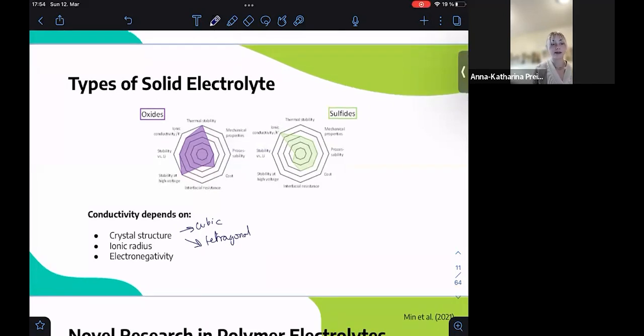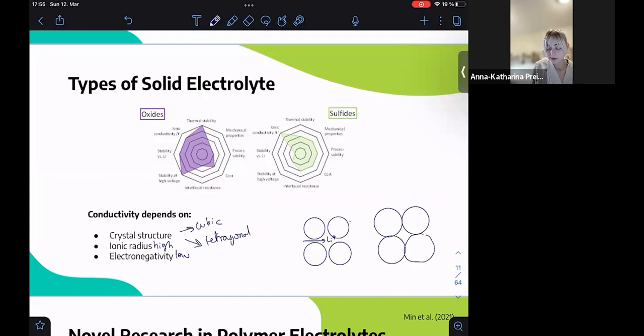Additionally, high ionic conductivities are related to low electronegativity and high ionic radius. This is because if we have a lower electronegativity, that means there's less attraction between, for example, a lithium ion passing through the crystal and the crystal atoms, so that it's more mobile throughout. And moreover, if we have large crystal atoms, this provides us with a larger tunnel in between them, giving a bigger pathway or easier access for that ion to pass through. So here, that's our large tunnel.